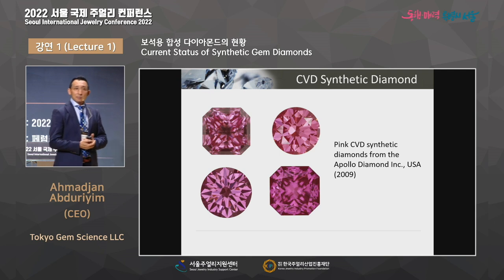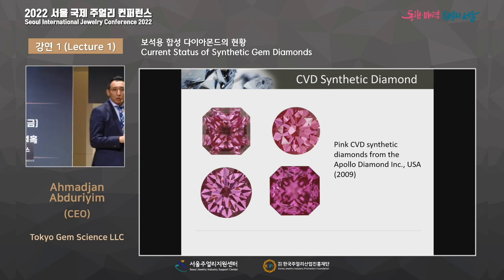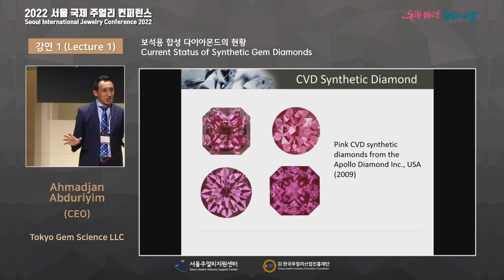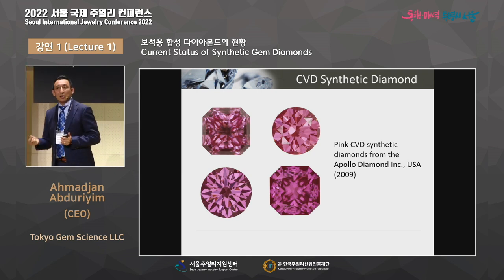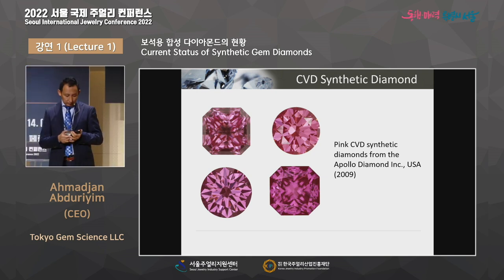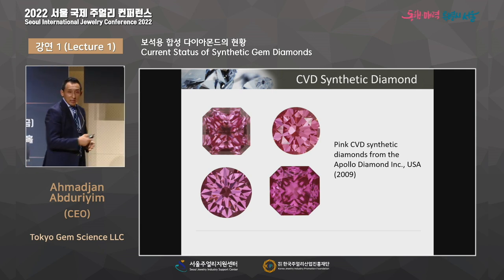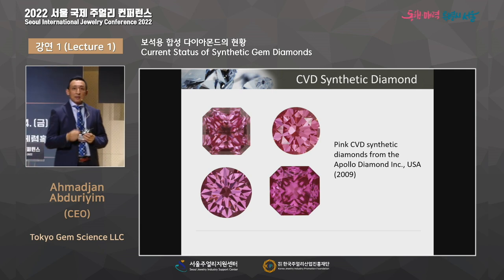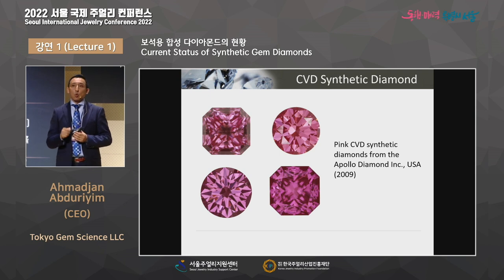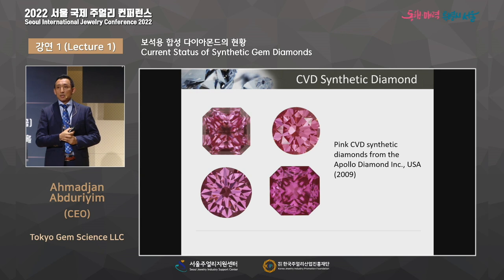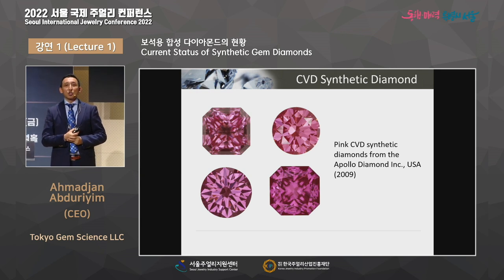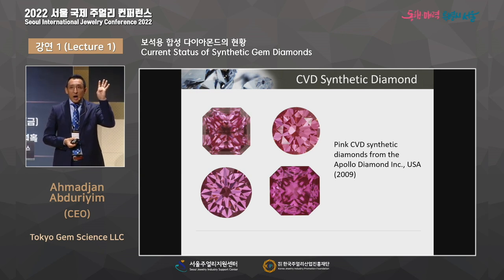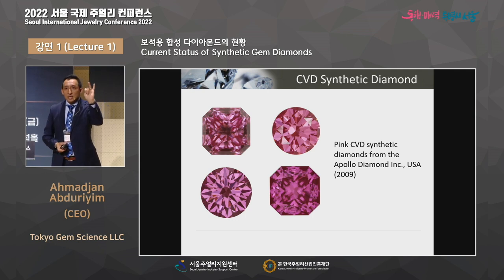And later, Argyle diamond almost closed, with no more production. They tried to make a similar color, like the Argyle pink diamond. They do the irradiation, then anneal this diamond up to 1,000 degrees to create this kind of pink. So CVD diamond originally starts from brown. After the treatment, they can make it colorless. After the irradiation and heating, they can make pink as well.